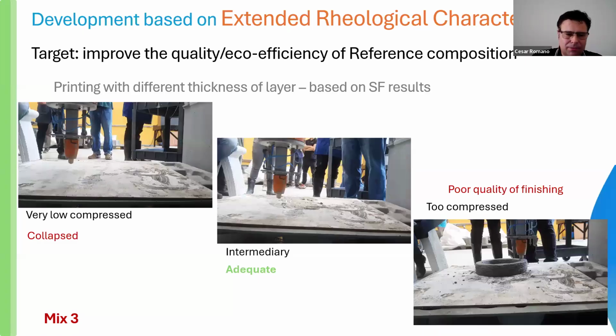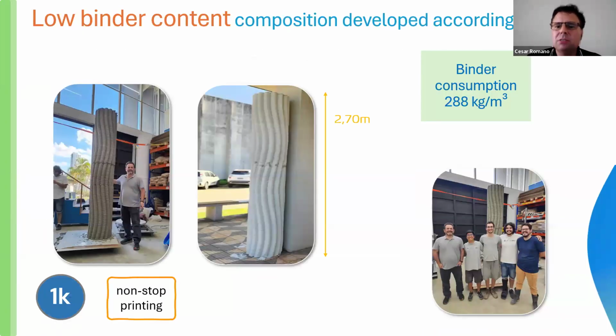Using this composition, this mix 3, was possible to print using a 1K system this pillar with a non-stop printing with very good quality and without using accelerating agents and with low binder consumption. And here is the team, very happy.